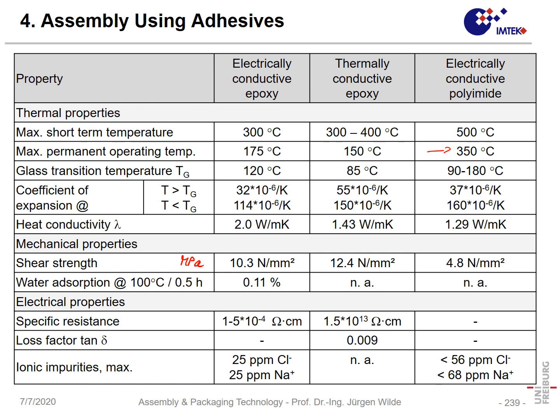So these silver-filled adhesives have a relatively low electrical resistance. It's higher than for solder alloy, but it's sufficient in all cases. What is also important is that while you use so-called no clean fluxes in soldering, here you must limit the content of chlorine, especially in these alloys, because chlorine in combination with silver can lead to severe corrosion problems. So here the chlorine content should be limited. For these adhesives, the glass transition temperature is relatively low. It can be between 80 and 120 or sometimes 150 degrees centigrade.